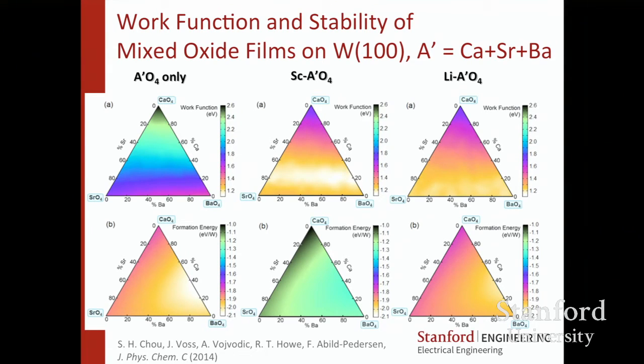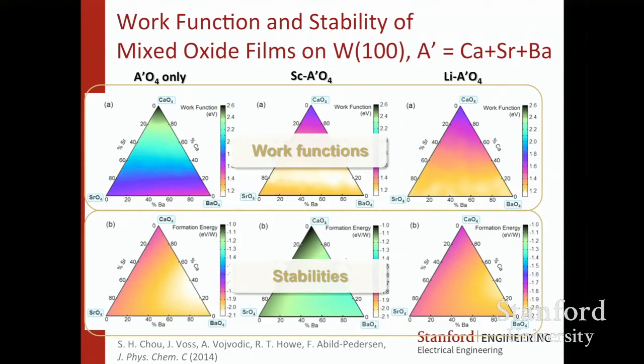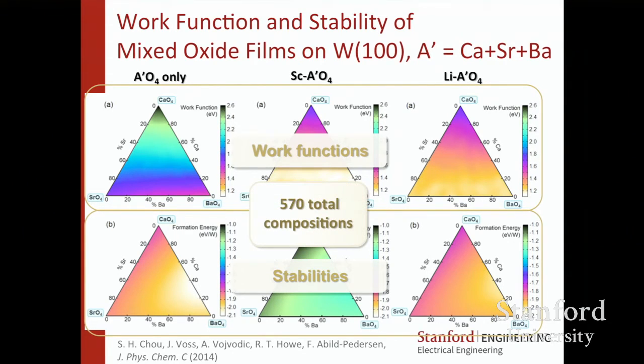So these are triangular diagrams of mixtures of barium oxide, calcium oxide, strontium oxide, and additional materials, sort of dopants, lithium and scandium, complex thing. This is all computed, not measured. And in fact, you have both of these and 570 total compositions. This is a paper in the Journal of Physical Chemistry. And for the people doing this, all of a sudden you have an arrow that says, try here first, right? We haven't mapped all of this. We do have some literature in selected parts of the space. But I think this is an example of why it's good to be doing your PhD in 2015.